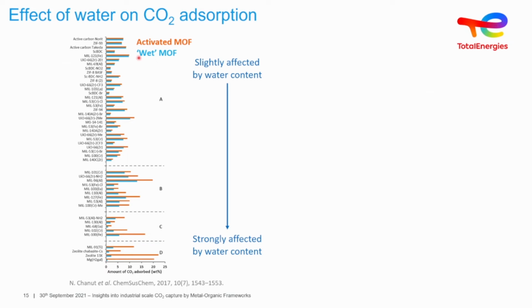And if we just look at the blue lines, so the CO2 adsorption with the MOF that's already been impregnated, which is wet, we can see that this material here seems to be of interest under our study, so MIL96. But also this material, these ones here, but also this material, MIL127 or SOCMOF.